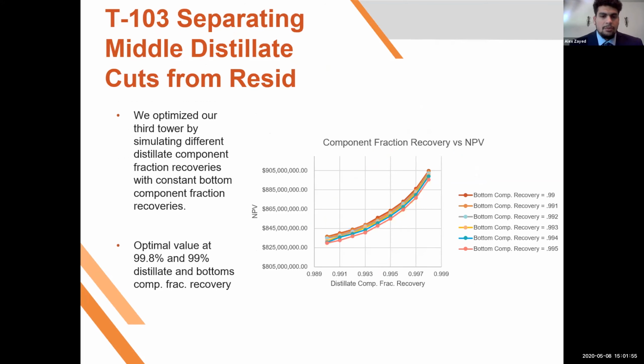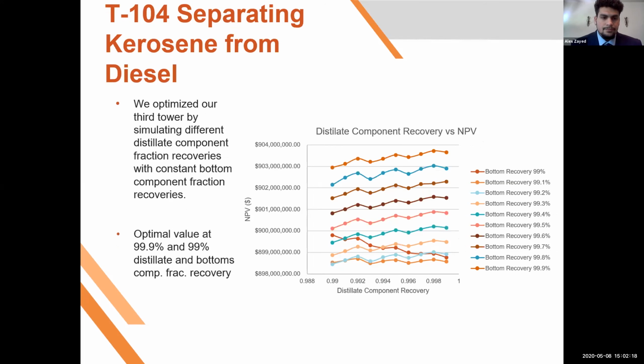So for tower 3, we used a similar approach as that first tower as far as optimizing. We took our fraction recovery in the distillate and compared it with various fraction recoveries in our bottoms versus NPV. As you can see, our optimal value is at 99.8% in the distillate and 99% in the bottoms, which makes sense because we have more valuable product in our distillate. Same thing for tower 4, separating the kerosene from diesel. Same approach: optimize the NPV by graphing our fraction recoveries in the distillate at various bottoms fraction recoveries. And as you can see, it looks a lot like the same graph from tower 1. We found an optimal value of 99.9% in the distillate with a 99% bottoms fraction recovery, which also makes sense because we have more valuable product in our distillate stream.